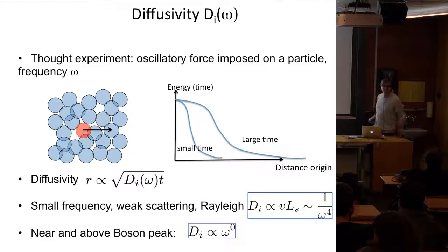So what should be the diffusivity? If you had a classical system at low frequency, what you get is Rayleigh scattering. You can think about a wave and perturbation theory on the scattering of a wave. What you find is that the scattering length would go like 1 over omega to the fourth. That's the same term that you learn when you think about why the sky is blue, for example. So in a disordered elastic system at low frequency, you would expect to have that, and there are experiments and data showing that you have that. But if you go to higher frequency, for example where you start to have those excess soft modes, then you find that the diffusivity seems to be flat.